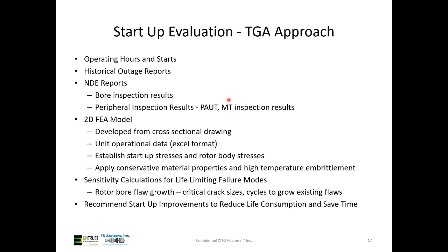Ultimately, what you do is something called fracture mechanics calculations, but it's looking at the flaws that exist and looking at what a critical flaw size would be, and then you can calculate kind of how many times you can cycle it to grow that existing flaw to a size of concern. If you don't have a bore, you may have a peripheral UT where they look from the outer surfaces inwards, again, to look for flaws internal to the rotor.